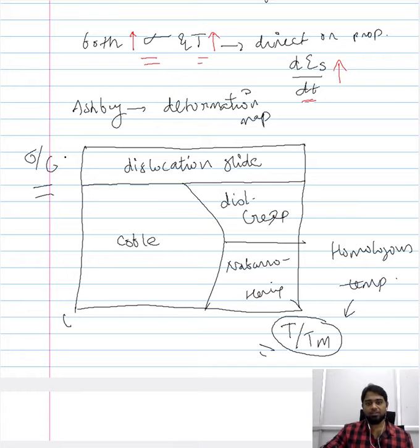Now here in this range, when you are considering a huge amount of stress or a higher stress region like this, the only mechanism that is operating is the dislocation glide. Irrespective of the temperature, given that the stress is relatively higher when compared to the other regions, the only mechanism that is operational is the dislocation glide. And here, as we could recollect, there will be an increase in the dislocation density, and the compensation that should come from the high temperature or through the recovery is rather restricted, and only annihilation plays a role.